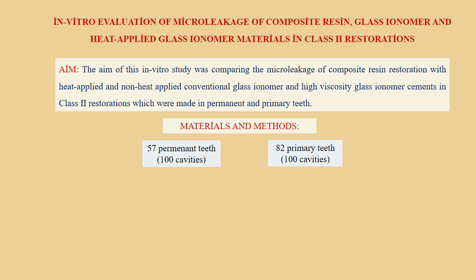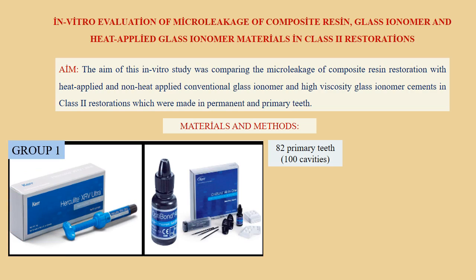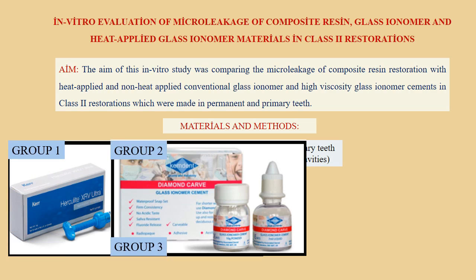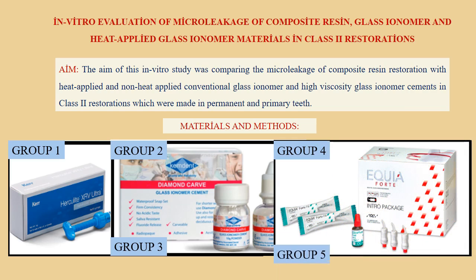For evaluation of microleakage, 57 permanent and 82 primary teeth were selected. Class II cavities were prepared using standard burrs. Teeth were randomly divided into 5 groups. Group 1 was applied composite resin. Groups 2 and 3 were applied conventional glass ionomer cements. Groups 4 and 5 were applied high-viscosity glass ionomer cements.